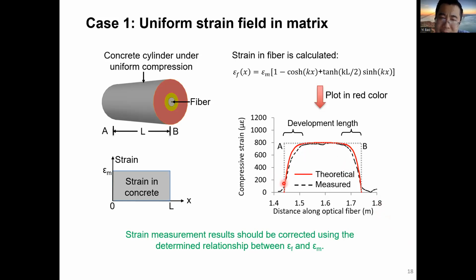And you can see that if the sensor has the point A and point B at the two ends of the cylinder, then at each end there's a development length. Within the development length, the measured strain is lower than the strain in the host matrix. So this is similar to the development length for reinforced concrete. Because of the development length, it is necessary to correct the sensing results. And for this simple case, we can do this correction based on the solved equation.